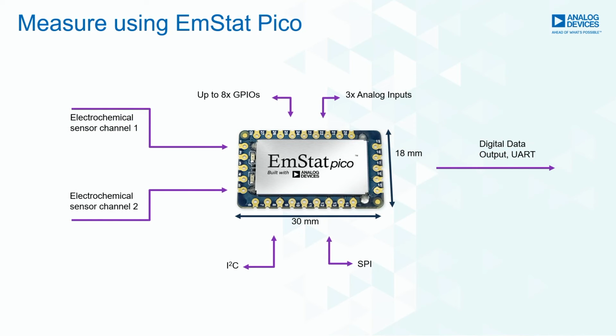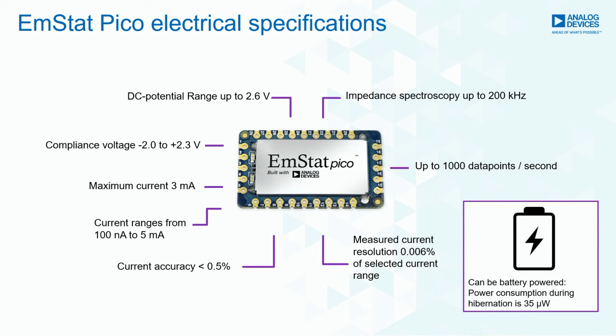Right. The EMSTAT Pico has two sensor channels where you can connect your working, reference and counter electrode, so 2 times. It has up to 8 GPIOs, it has 3 analog inputs, you can have a digital data output, UART connection, you have SPI connection and an I2C connection. The parameters of the EMSTAT Pico are very good for its size, but of course if you compare it to the very large potentiostats, it has a smaller potential range. But what is very impressive for electrochemical devices with this size, it can go up to 200 kilohertz while doing impedance spectroscopy. It can record up to 1,000 data points per second.